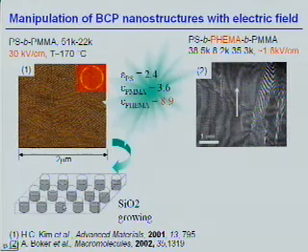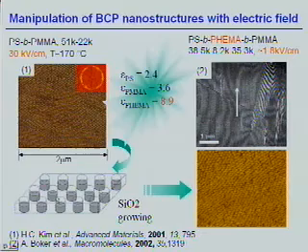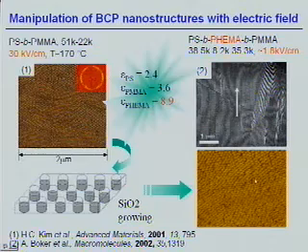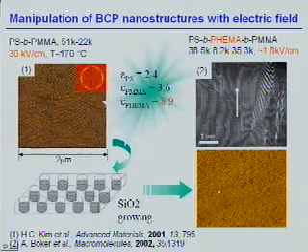Then in these pores, if you can manage to deposit some materials you like, as in this case they deposit silicon oxide, we can form this ordered array of silicon oxide. Furthermore, we can remove the matrix components, the polystyrene. So in this picture, we can see these highly ordered silicon oxide posts. They are aligned in this area.